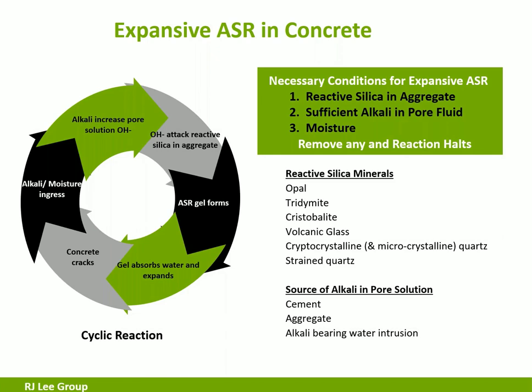Now, the source of alkali in the pore solution is going to come mostly from the cement, but we're studying more and more where that alkali could come from the aggregate. And also, you'll get a little bit of alkali-bearing water intrusion in certain circumstances.